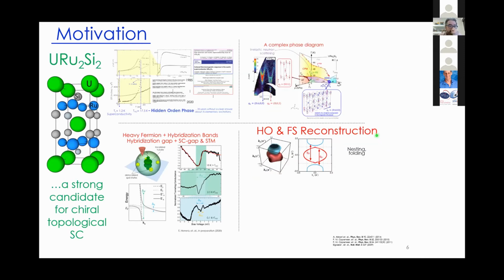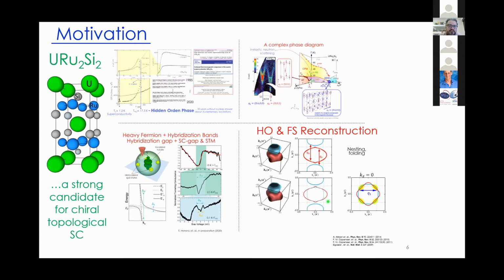So, what about the hidden order phase and the Fermi surface? In this compound, the Fermi surface is reconstructed due to a nesting between different parts of the Fermi surface. This nesting occurs precisely in these Q0 directions, and the overlapping of the two parts generates hotspot regions that we represent here in yellow on the kx-ky plane, and they are also connected with this Q1 vector that we have represented here. So this Fermi surface reconstruction allows the opening of gaps in different directions.